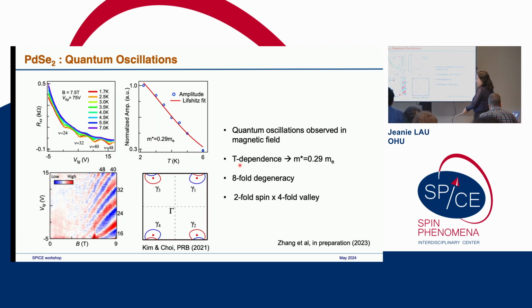Okay, so with that kind of mobility, we can do quantum oscillation measurements. What's interesting is that the oscillations turn out to have 8-fold degeneracy, which was unexpected. So what happens is we have 2-fold for spin, and there's 4-fold for valley, and this comes from the valleys in this Brillouin zone, from the square lattice. So we have 4-fold valleys, so I think that's kind of interesting. And we can measure the effective mass is about 0.3.